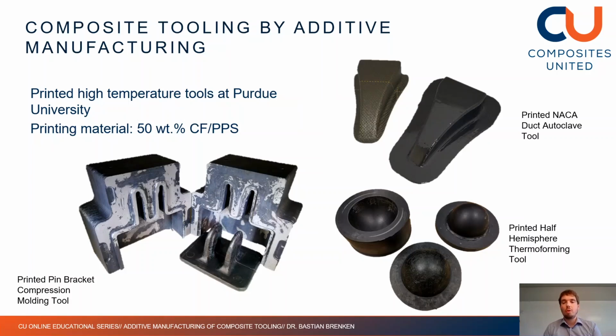For instance, thermoforming. On the bottom right you see a printed half hemisphere tool. This is a two-sided tool, so it has a female and a male part. And then we heated up this sheet of discontinuous carbon fiber material, and we put it in, and we were able to mold it at higher pressures than autoclave pressures.